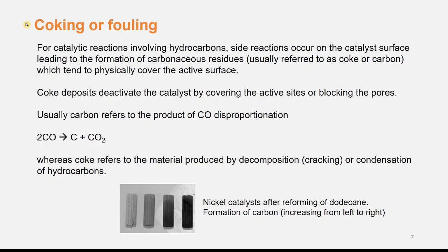Let's look at coking in more detail. Coking or fouling typically occurs in catalytic reactions involving hydrocarbons, where side reactions produce carbonaceous residues, usually called coke or carbon, that are deposited on the surfaces of the pores, covering the catalyst's active sites and eventually blocking the pores completely.